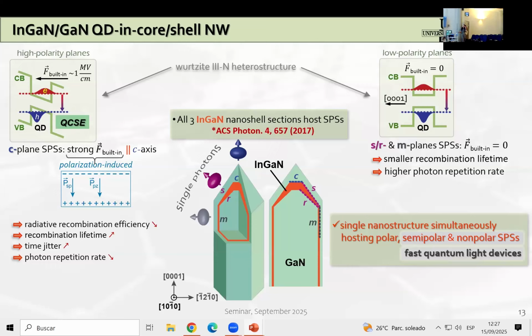Now, the reason why it is necessary to also have the semipolar and the non-polar quantum dots is because the polarization-induced built-in field, which has a very strong value for polar quantum dots, so those that are grown on this plane here, does not exist in the case of non-polar and semipolar facets, or is significantly reduced. So what basically happens in polar quantum dots, because of the strong built-in electric field via the quantum confined Stark effect, is a significant spatial separation of the electron and hole wave functions, which essentially leads to the reduction of the photon repetition rate. Therefore, it lowers the speed of the quantum devices.